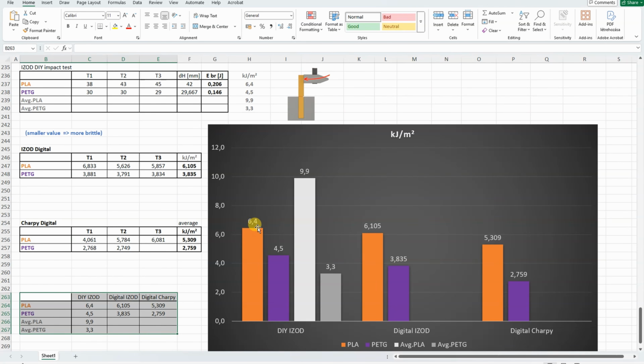Now this PLA is more brittle compared to the average PLA, but here many crazy PLA types are included, like, I don't know, Super PLA Plus by Overture or similar. The PETG is typically more brittle, so this PETG is tougher compared to the average PETG. And with the brittle filaments, I'm getting more or less very similar numbers with the digital IZOD and the Charpy. Of course, this is a completely different test type, but with the brittle materials, similar values.